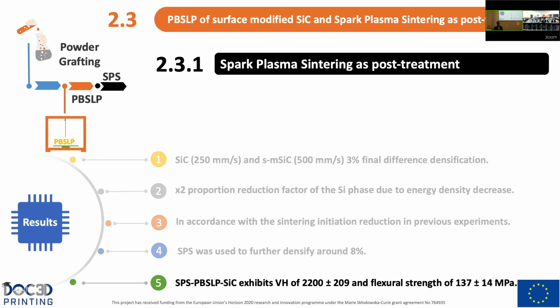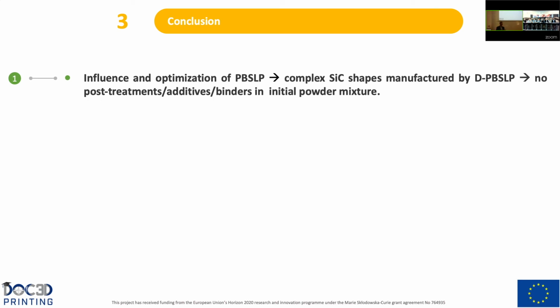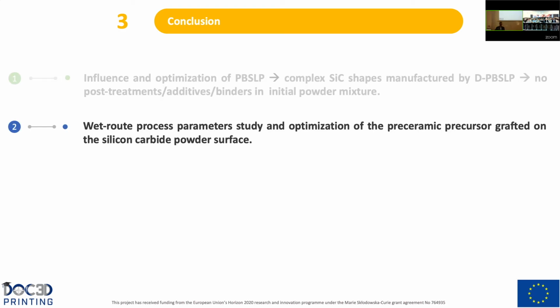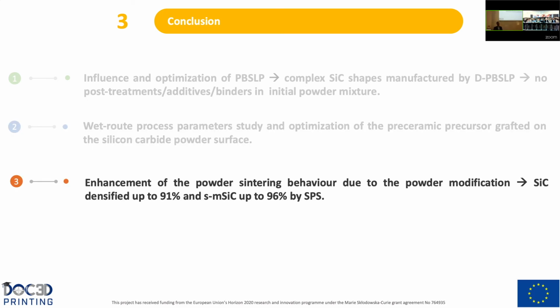So regarding the conclusion of the experimental parts of this project, we have studied and optimized the process parameters of powder bed selective laser processing. Now we can confirm the process viability because we are able to manufacture complex silicon carbide shapes by this technique without post-treatments, without additives, and without binders in the initial powder mixture. Next, we have studied and optimized the wet process parameters to graft the preceramic precursors on the silicon carbide surface. We have studied and we have seen the enhancement of the sintering behavior due to this powder modification.